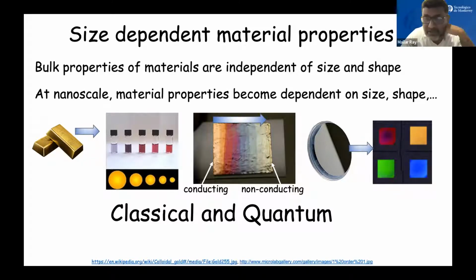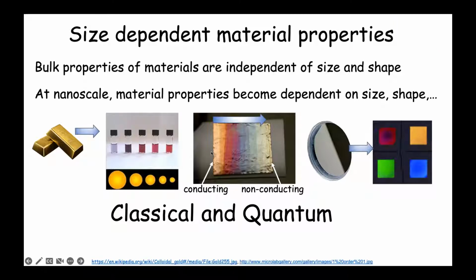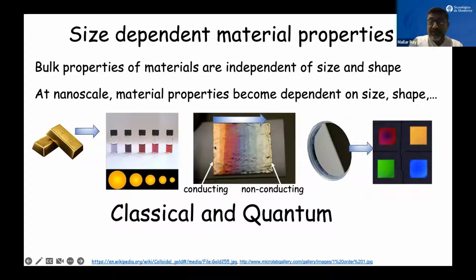The human civilization knew how to make gold nanoparticles. But these characteristics, the plasmonic colors, can essentially be explained in light of classical electromagnetic theory, although the plasmon modes are quantized. On the other hand, if you look at a typical change of conductivity of copper when its size is reduced, from highly conducting copper to non-conducting copper made of nanoparticles, there's a huge change in conductivity. Here we cannot explain it in classical terms. It's a typical quantum mechanical phenomenon.